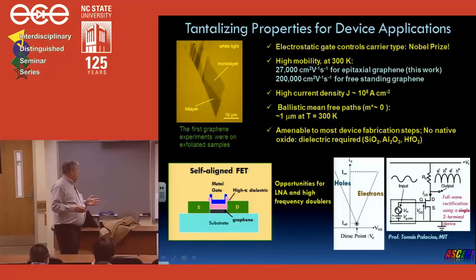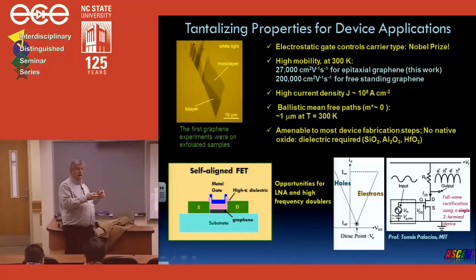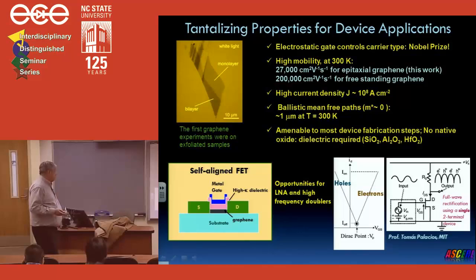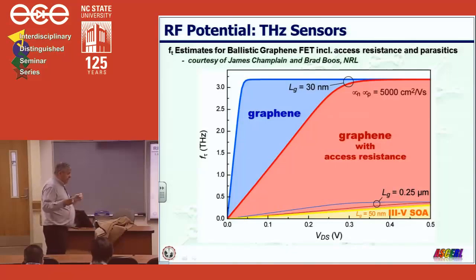One area I just happen to mention is because you have a very symmetrical IV response for graphene. That means it becomes very attractive for making frequency doublers or mixers, and that becomes valuable if you need to up convert or down convert signals from high frequency to low frequency. The thing that got us very excited about graphene is that for low applied drain source voltages, you have in principle the ability for extremely high cutoff frequencies.